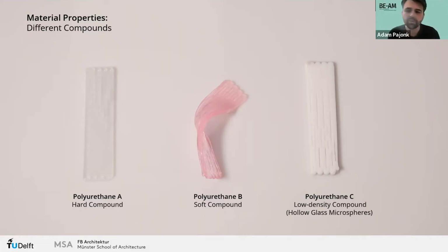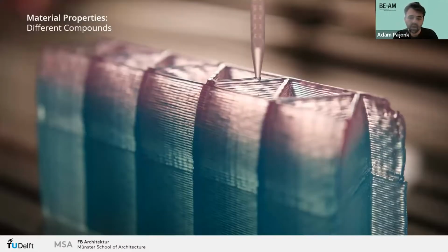And while polyurethane has the ability to create a foam with a very low density just by using a foaming agent, tests that we conducted led to several problems with this. Specifically, the process of foaming itself is rather difficult to control, and especially to use if the intention is to create a rather accurate object. So therefore, we decided to, for this moment, stick with these hollow glass microspheres as an additive.